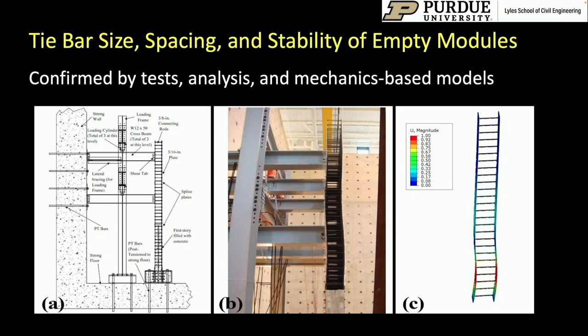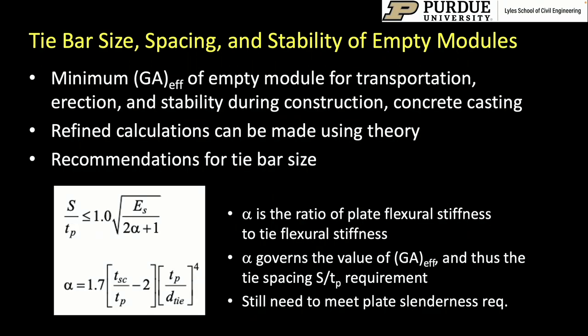And you just saw the testing that had been done by my colleagues earlier. That experimental data combined with numerical models, we were able to combine all this information in order to develop simple recommendations for the design of the system as an empty steel module in order to have adequate stiffness and strength during concrete placement. So this minimum GA effective is now part of the code recommendation.